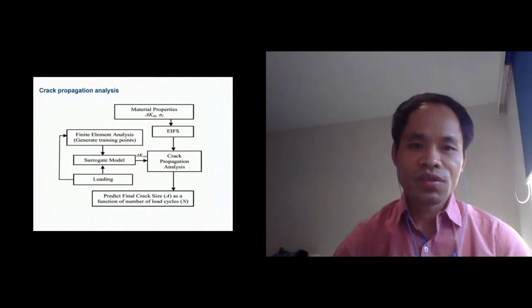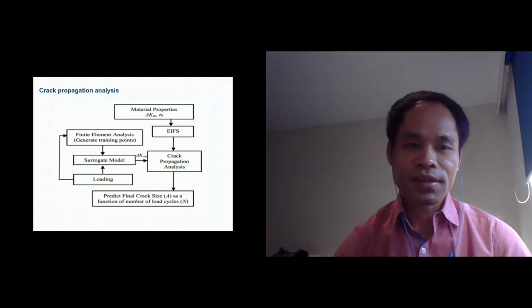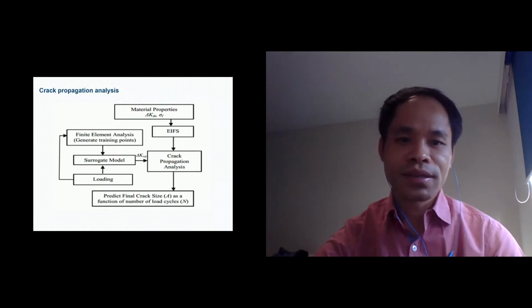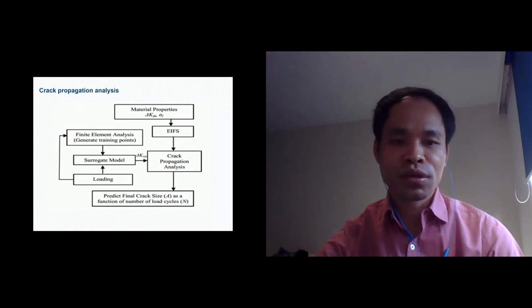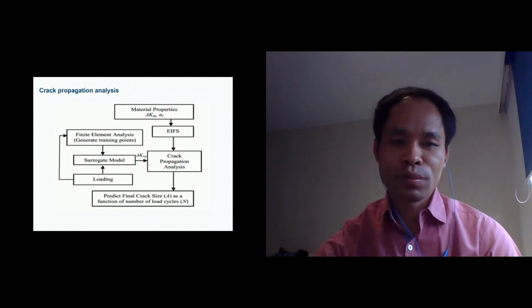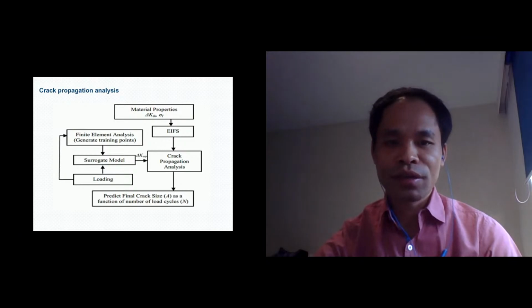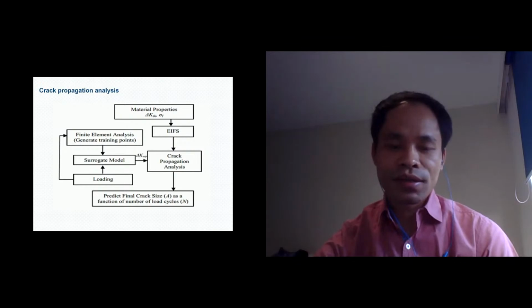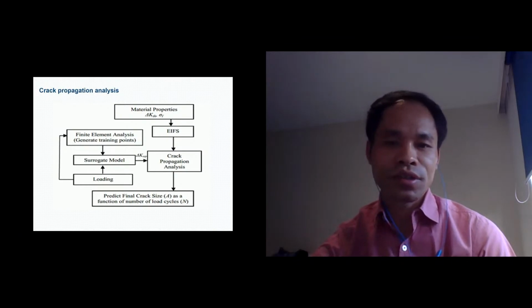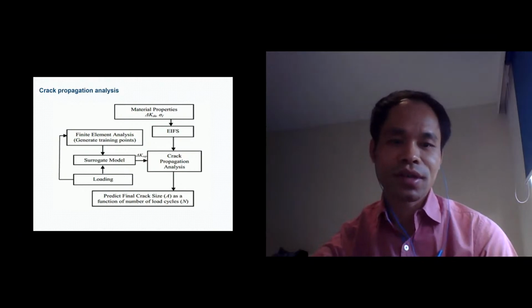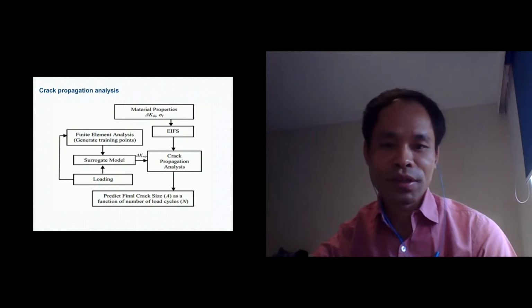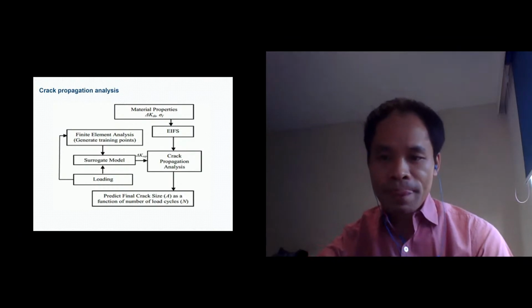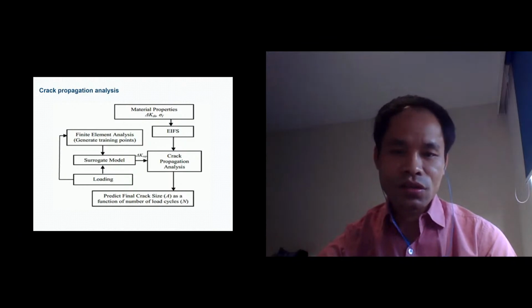So now, how people try to evaluate this crack propagation is that some try to modify the basic models, and some others try to model it through FEA. In this research, they say they can predict the crack size using a surrogate model built from FEA, and then utilizing the material properties and the equivalent initial flaw size. So this is how they do it. They say these models can predict the crack size, but they do not account for the errors and sources of uncertainty, and this model is deterministic.